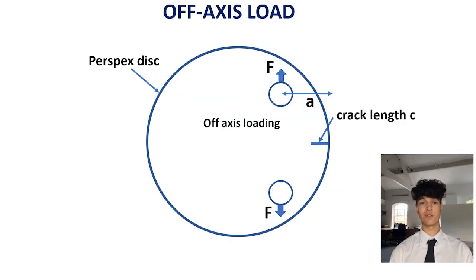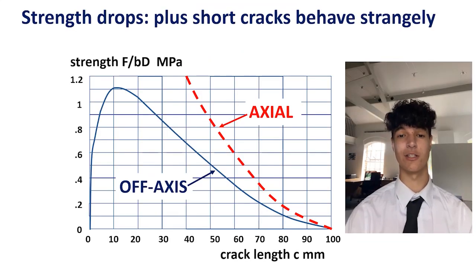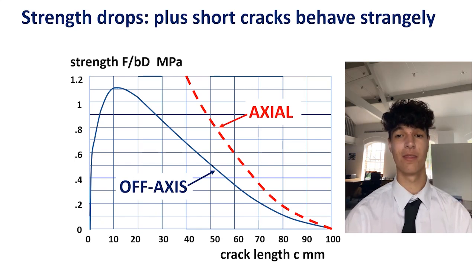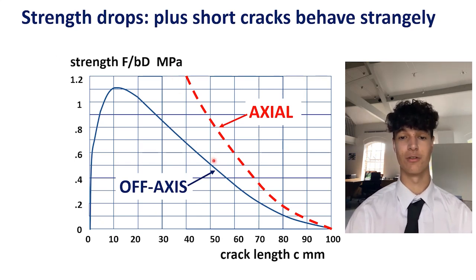The most interesting result is for off-axis loading. Here, we had to take into account the distance A, the distance of the force application from the edge of the disc. This calculation shows very interesting new behaviour. First, the strength falls below the axial curve. The sample is weaker in off-axis loading.